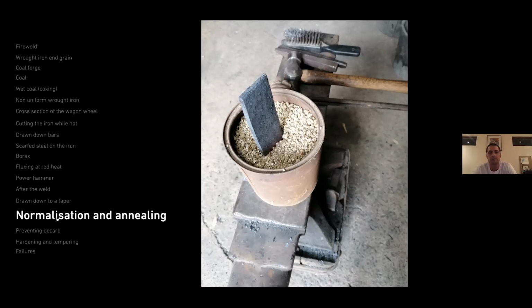A lot of other laminated blades, such as knife blades that one sees, which are laminated hard steel in the center and soft down the edges on each side, sort of counteract the pull. When you quench a blade like this, if it's not completely normalized, the hard steel shrinks while the soft steel sort of carries on moving a bit as it's quenched. The hard steel shrinks and freezes in that position, and the soft steel shrinks and then expands a bit, which makes it banana. And it always becomes concave on the soft side, convex on the hard side, which is the opposite of what makes it easy to then grind out.